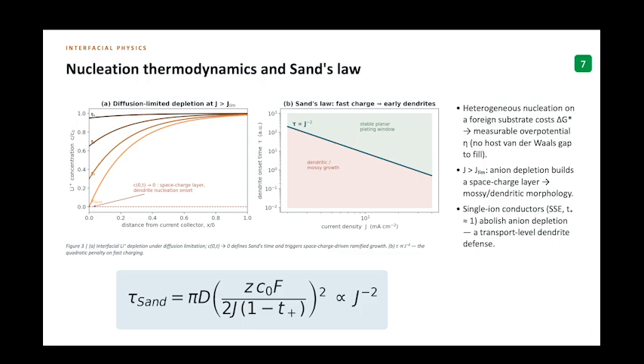On panel A, what you see is that when you charge fast, ions get consumed at the surface faster than diffusion resupplies them. Concentration at the copper crashes towards zero, a space charge layer forms, and the growth goes chaotic. Needles, moss, and dendrites. And there's an equation for exactly when: Sand's law, shown on panel B. Dendrite onset time scales as 1 over current density squared. Double the charging speed, and dendrites show up 4 times sooner.